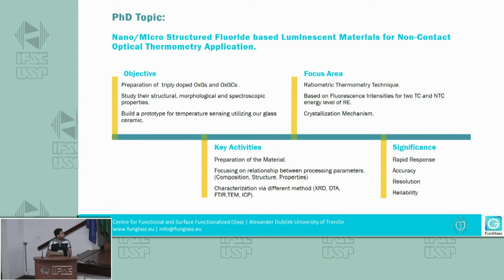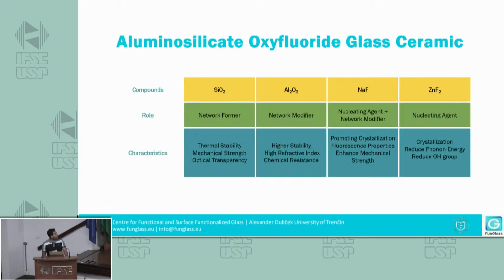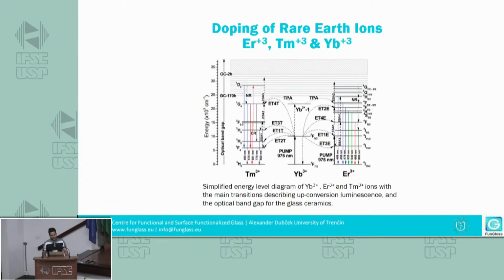The key activities include the preparation of the material and focusing on the relationship between the processing parameters, and characterization by different methods. The significance of this research is to develop a prototype with rapid response, accuracy, resolution, and reliability. Here I have selected the aluminosilicate oxyfluoride glass ceramics, and the doping elements are erbium, thulium, and ytterbium, and this is showing the possible energy transfer mechanism. Ytterbium will act as a sensitizer to have some upconversion luminescence properties.